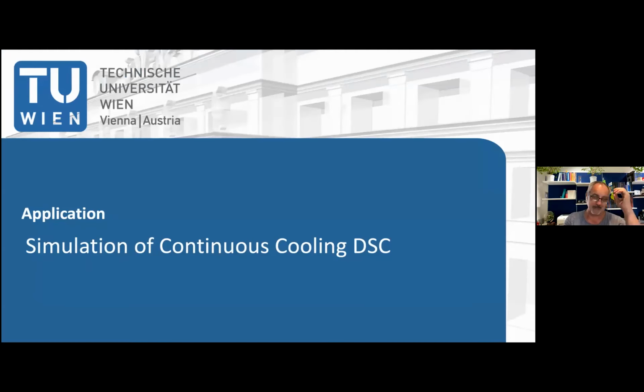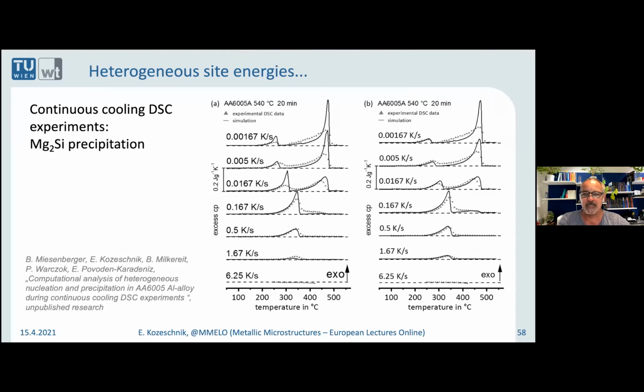And now comes the reason why I have gladly accepted this short-term invitation to give the presentation, because I was working on some data that was published by the group of Benjamin Milkereit. He was doing continuous cooling DSC experiments in the 6000 aluminium system. What you can see here is the DSC signal, the experimental points, as a function of the cooling rate. So there's a lot of variation in the cooling rates. And I'm particularly interested now in this slow cooling region.